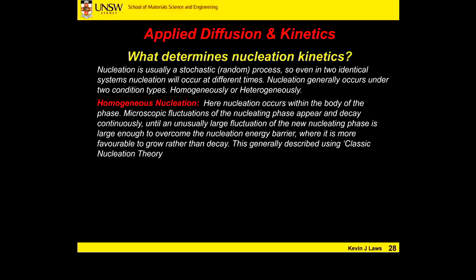So little crystallites will appear and disappear as the material's in equilibrium, approaching, say, a solidification temperature, until some point where one of those sites will be big enough, or you might have two nucleation sites very close together, creating a localized energy. They might combine. And then we hit our critical size for nucleation to occur.